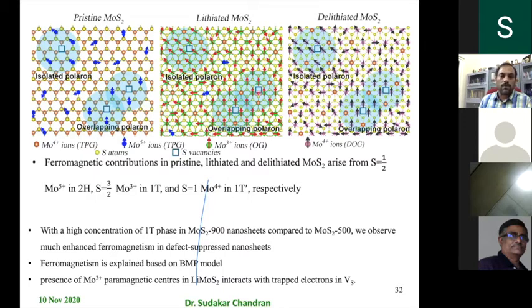So therefore a large increase in the magnetization is seen in this state. When you go back to the delithiation state, the Mo4+, this still has 2 unpaired electrons. Therefore there's a slight reduction, but then still you will see that the ferromagnetic state is retained.